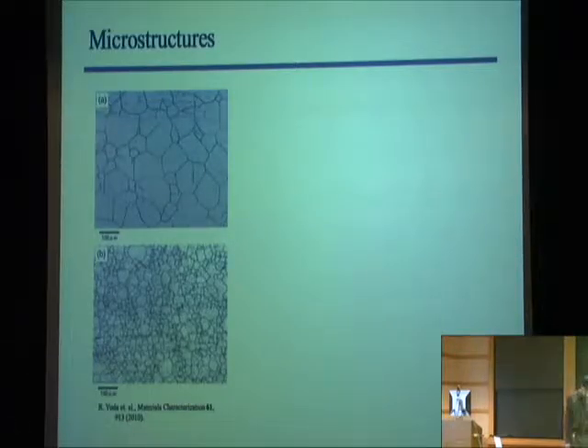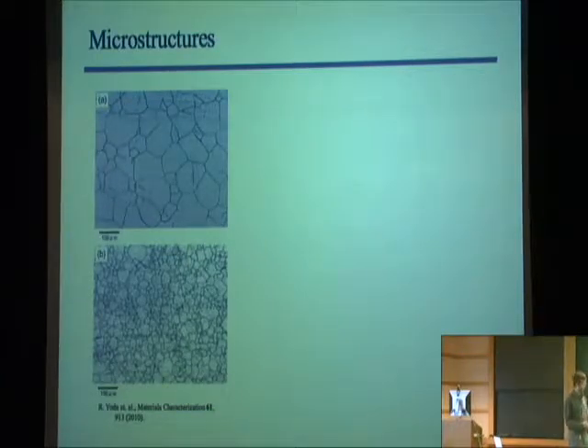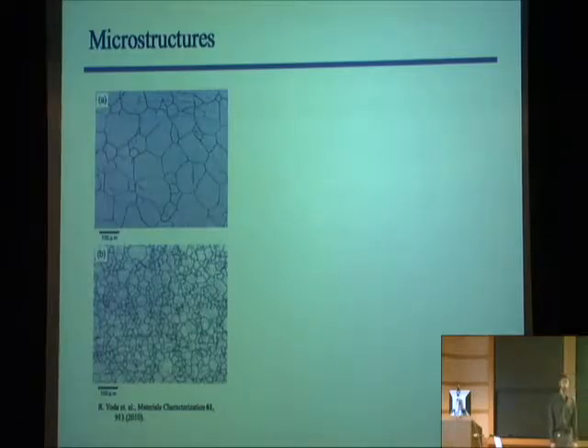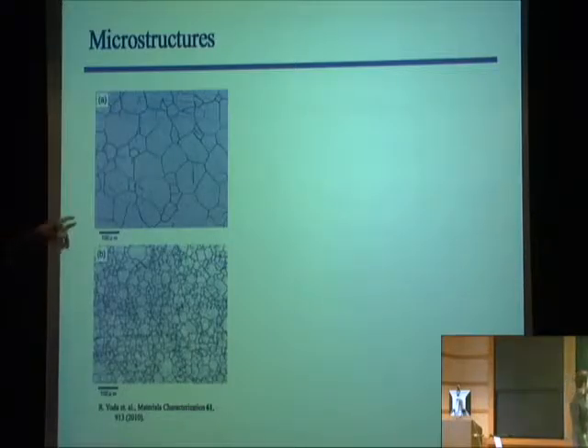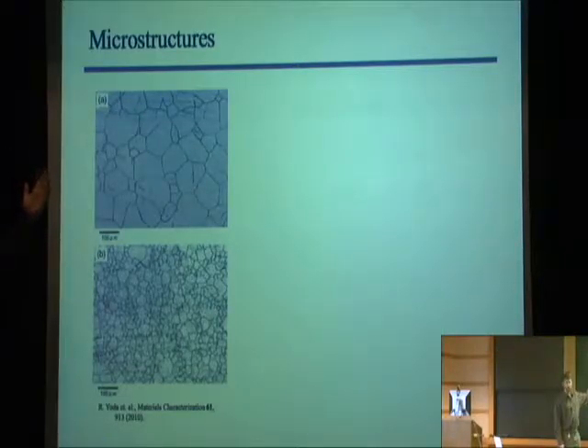The reason this is pertinent to materials is because if you take a metal — almost any metal that you would encounter in your day-to-day life — and you take a section of it, so we have some planar surface, and you treat it with various kinds of acid baths and look under a microscope, you see a structure like this. This is the structure on the level of a micron. These bars here are actually 100 micrometers, so we refer to this as the microstructure. The microstructure is composed of these individual cells or grains — single crystal grains — and the interfaces on which these meet, which we refer to as grain boundaries. You look at this and you see that the grain boundaries form some three-regular graph.